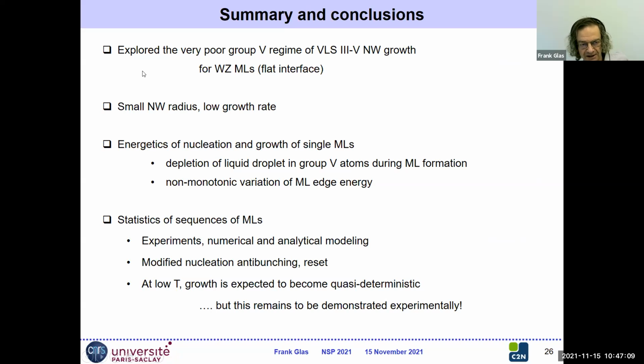So in this talk, we explored the very poor group 5 regime of VLS growth, which seems to be more common than what we expected before. We expect it to happen in nanowires with small radii at low growth rates. We have looked at the energetics of nucleation-limited growth of single monolayers, and we have seen that in this small system, there are 2 important effects: depletion of the liquid droplet when you start growing a monolayer, and decrease of the chemical potential, but also the non-monotonic variation of the monolayer edge energy, which we have to take into account.